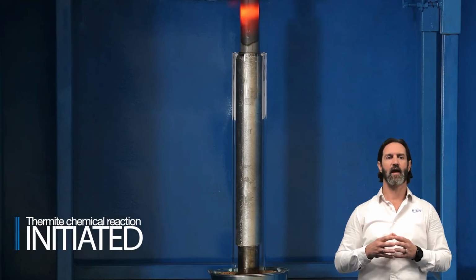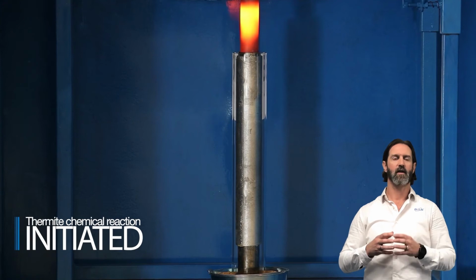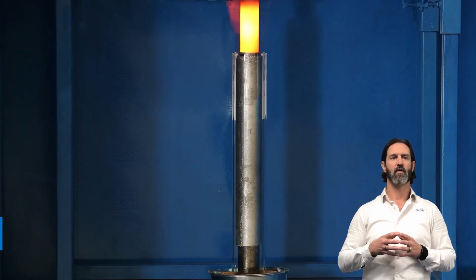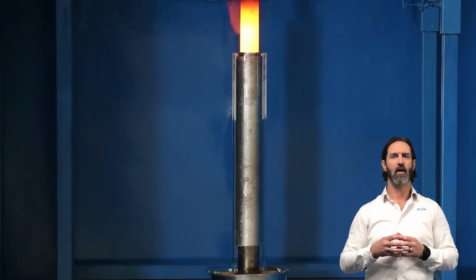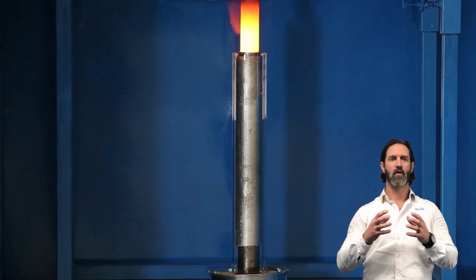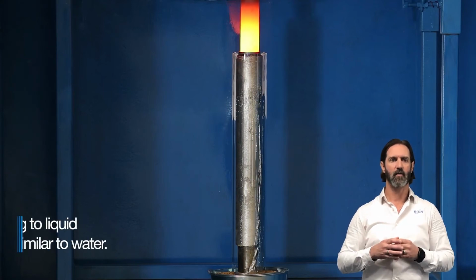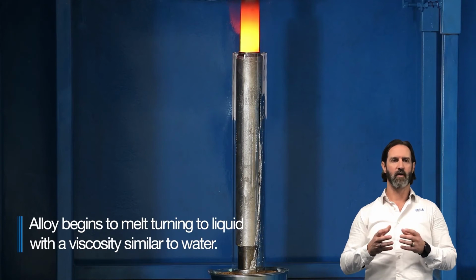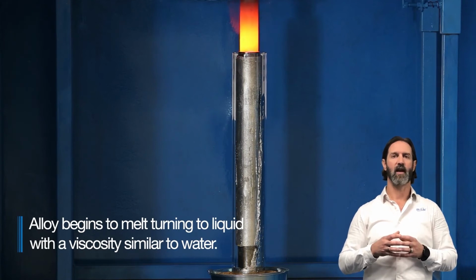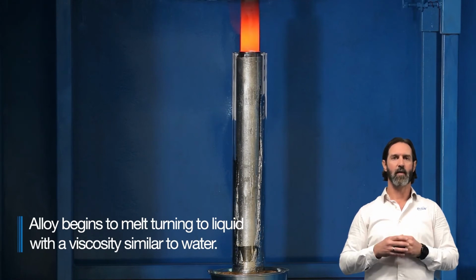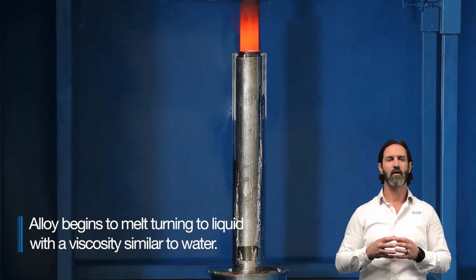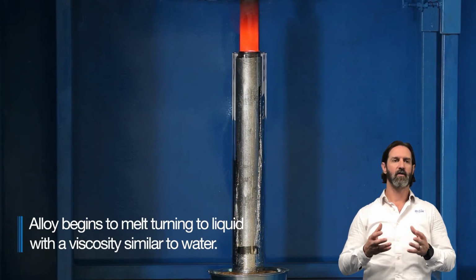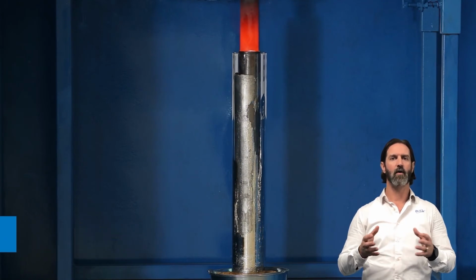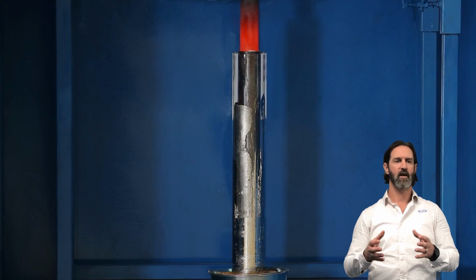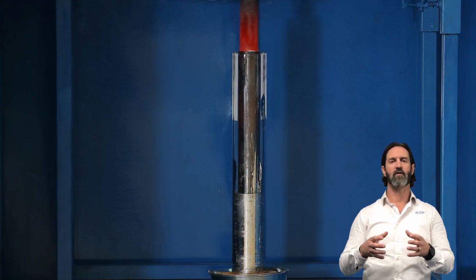What happens when you light a candle? As you can see, the heater starts burning down just like the wick of a candle. Then as it reaches the top of the alloy, that alloy begins to melt and drip down the side of the candle. You'll notice that all of it doesn't run to the bottom. A lot of it stops on the side of the candle, or on the side of the tool, just like a candle would. That's that eutectic property, making it solidify very quickly. It then continues to burn down, continues to remelt until you have all of the alloy left at the bottom of the heater, and that's where your plug is actually being formed.